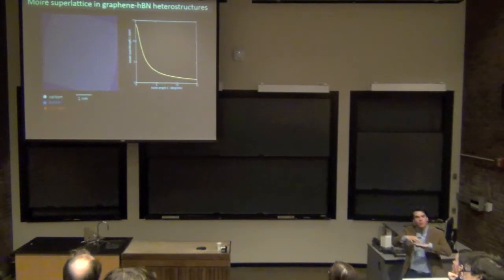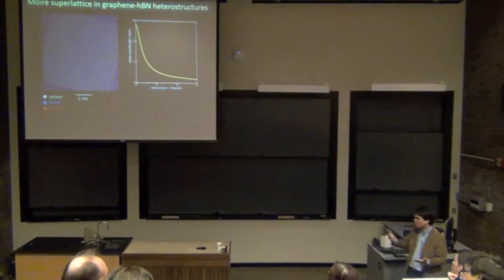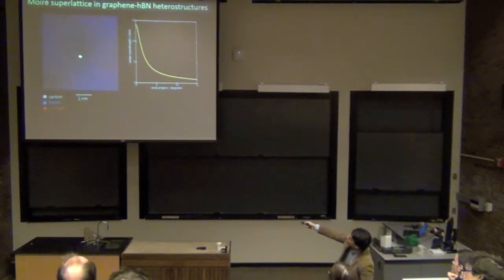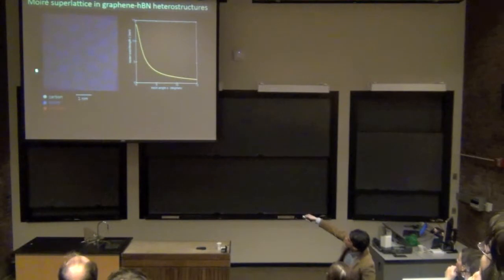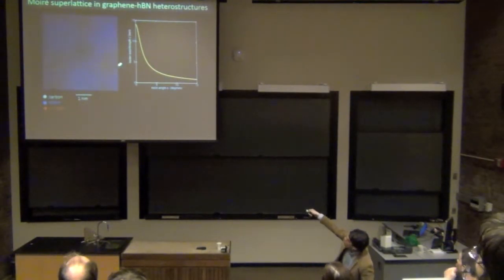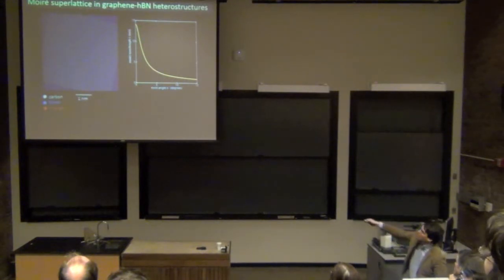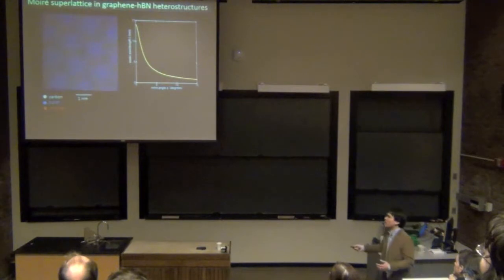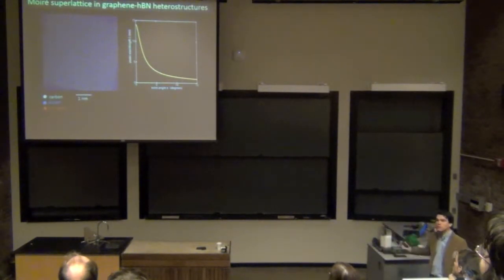As you might know, when you superimpose two periodic structures, generically what you get is a moiré pattern. I hope you can see it, I hope it's not too dark, but you can see as a function of the twist angle between the graphene and the boron nitride layer that there's this sort of superstructure. And the closer that you twist the layers into alignment, the longer this moiré pattern, the superstructure, becomes. And again, this is a very generic feature of two superimposed periodic structures.